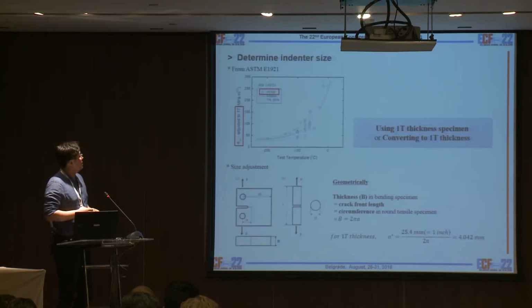And also in this case, we determine the indenter size with the 1T thickness specimen from the standard. This is controversial, but usually we use the 1T thickness specimen for brittle material. So in the case of a cracked round bar, the thickness is the circumference in a round tensile specimen. Then finally, we determine the A star as 4 millimeters, like a validated radius indenter.